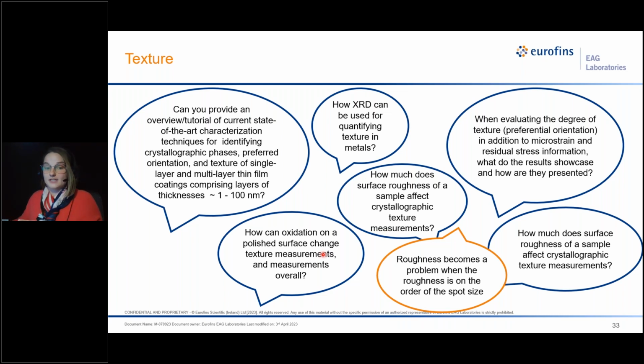And next, we're going to talk about texture. Now, there's a lot of ways to analyze texture. This is not roughness of the actual surface of the sample. This is orientation of crystallites, is what we talk about when we talk about texture. Roughness only becomes a problem with the texture measurement when it's on the order of the spot size. So essentially, if you have roughness of 50 microns, but your spot is also 50 microns, you're going to have an issue trying to get enough crystallites to get the actual information from the texture that you need.